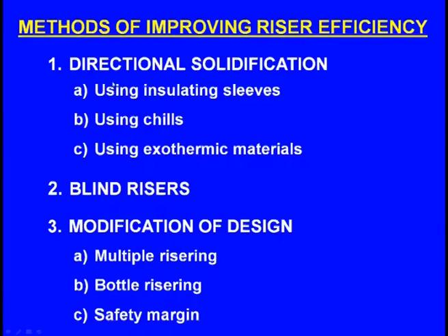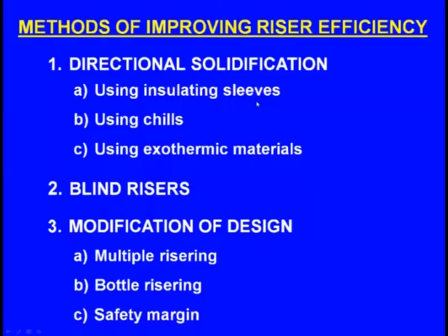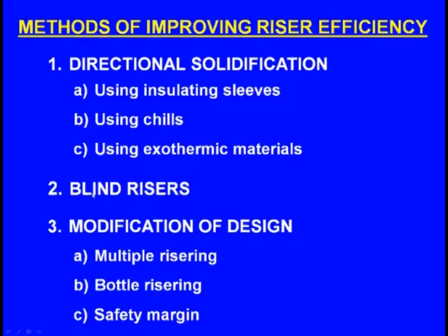We have also seen the methods to improve the riser efficiency. The riser efficiency can be improved by achieving directional solidification. Directional solidification can be achieved using insulating sleeves, using chills, and also using exothermic materials. Next, the riser efficiency can be improved by adopting blind risers. So, this is what we have learned.